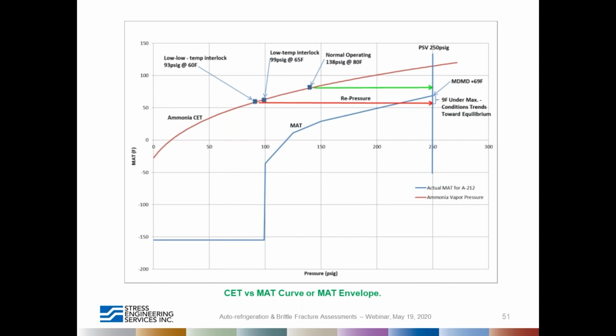So the normal operating pressure and temperature is 138 psig at 80F. If you repressurize it to the PSV set point, then the vessel is not at risk. However, if you go to a low temperature interlock where the pressure is 99 psi and the temperature is 65, you are at risk of brittle fracture. So it's just illustrating how important it is to develop a MAT curve and look at it from the standpoint of process hazard analysis when the vessel was not designed to address these concerns.